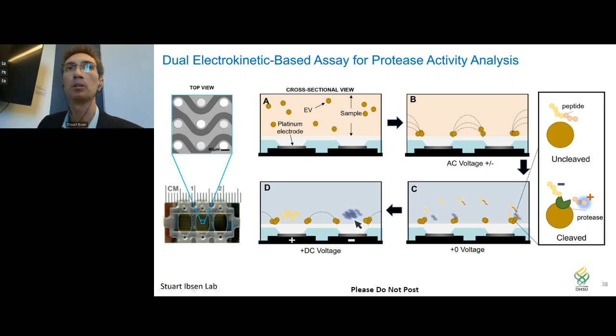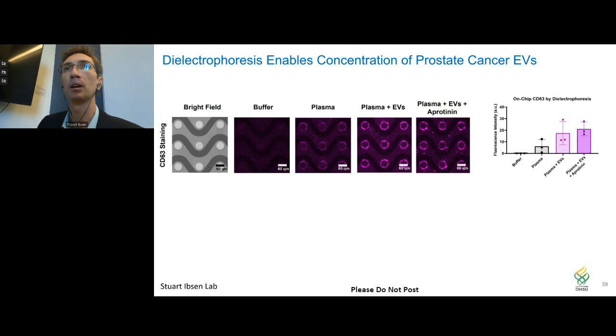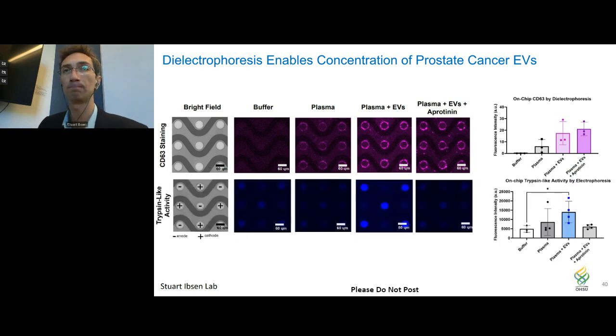And that's exactly what we show here. So here we show the collection of these extracellular vesicles from plasma, as we were demonstrating before. And then we can introduce our peptide to this sample and do electrophoresis to collect these positive fragments on the negative electrodes. And this is really great because it gives us a signal amplification. Because we concentrate these fragments, we get a better signal as to whether there is any protease activity of the specific kinds that we're interested in.